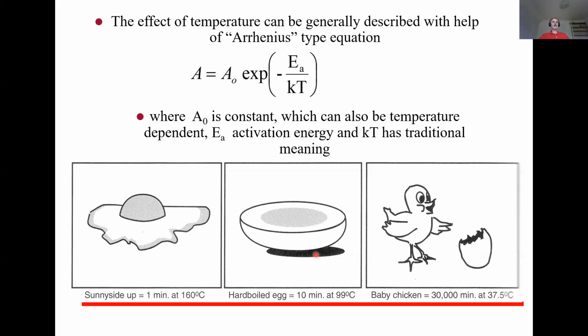But as this is taken, if I recall correctly, from Tummala's handbook, you need to really understand this activation energy term is for one single mechanism. So it's only applicable to one mechanism, which means that it's also applicable for a certain temperature range. So we all know what happens to an egg depending on the temperature. If you keep an egg at, let's say, 37 degrees for a long time, you end up having a baby chicken. If you put it in boiling water, this process is not accelerated. You are not getting a baby chicken after certain minutes, but you have a boiled egg. If you put it in a frying pan, you get a fried egg.